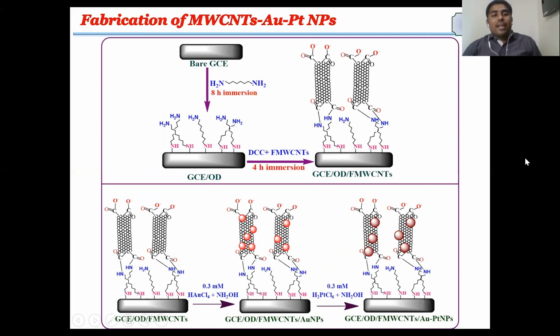Further, we fabricate the gold platinum nanoparticles on a carbonaceous material, multi-walled carbon nanotubes. Initially the multi-walled carbon nanotubes were acid functionalized, and then fabricated on the electrode surface with the help of the octane diamine linker and DCC coupling. With the help of DCC coupling, the multi-walled carbon nanotubes were fabricated on the surface of the GC electrode. Then the electrode is immersed into the solution of chloroauric acid and hydroxylamine for the formation of gold nanoparticles on the surface of multi-walled carbon nanotubes.